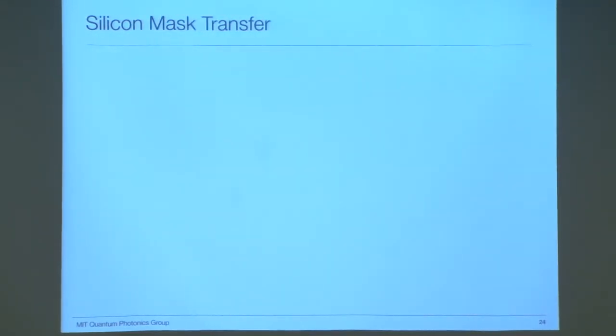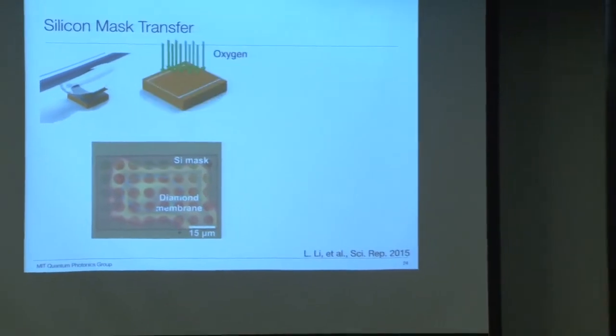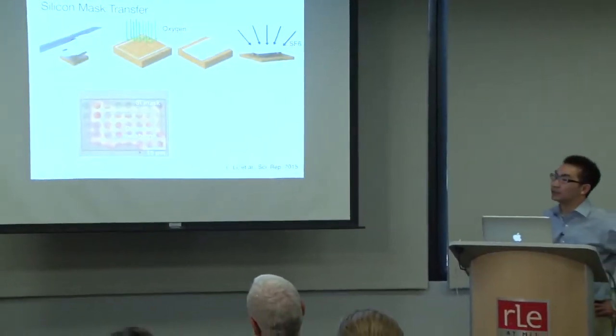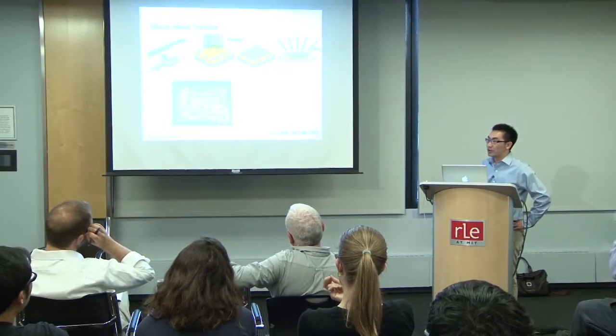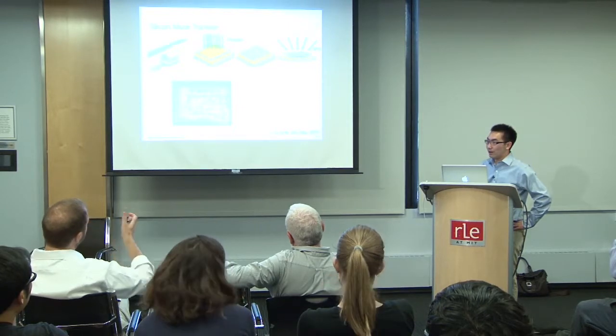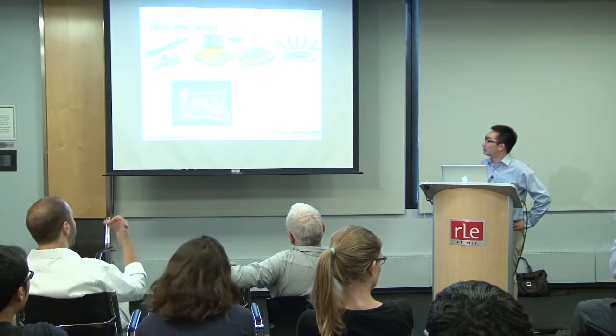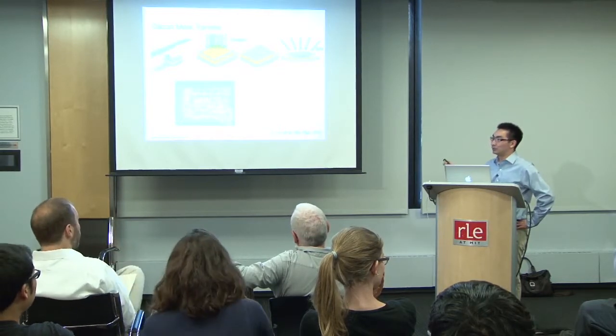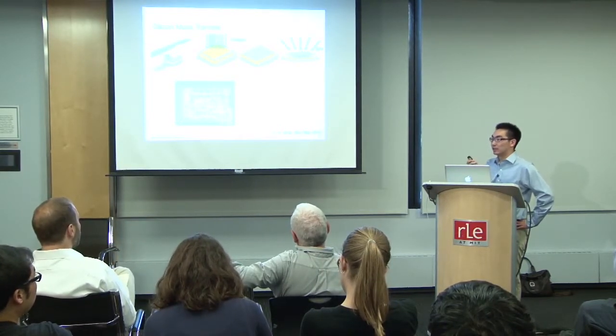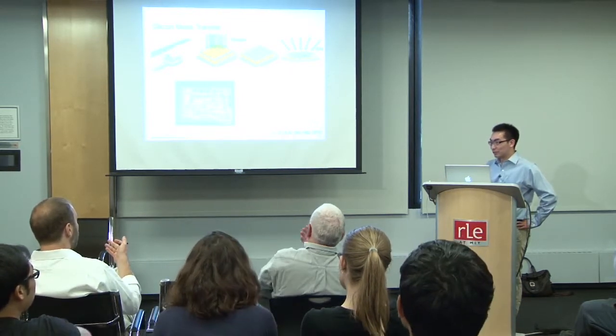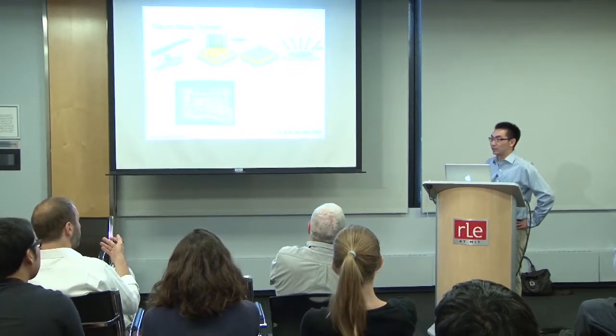Sorry, I missed something, I was taking notes. What was the SF6 for? The SF6 removed the bottom silicon to suspend the diamond membrane at device locations. So the diamond membrane is put down on silicon, and then silicon is put on top of the diamond membrane. Yeah. And then we use oxygen plasma to transfer the pattern from silicon into diamond. We mechanically remove the silicon mask, and then we use SF6 to undercut the bottom silicon. All the way, or just partially? Just partially, at the device locations.